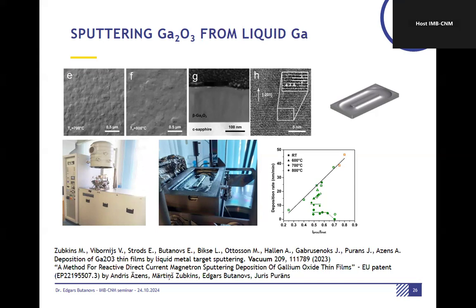Okay, so we developed a specific container, since the melting point of metal gallium is around 30 degrees. So in realistic sputtering conditions, it will typically be in a liquid state. We have developed a specific technique to sputter a liquid metal. It's very nice. We can get very high deposition rates, decent crystallinity. There are some defects from the bombardment. We are fine-tuning the process, so these results were at higher power. If we use the lowest deposition power, at very slow rates, the crystallinity is much nicer.